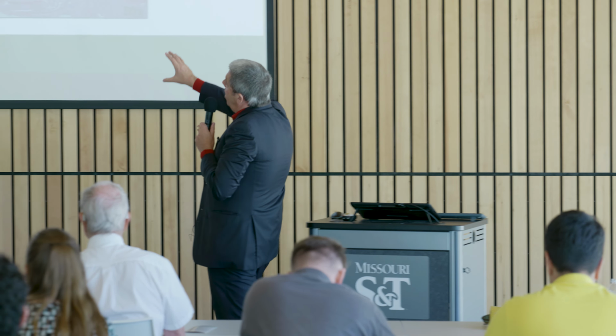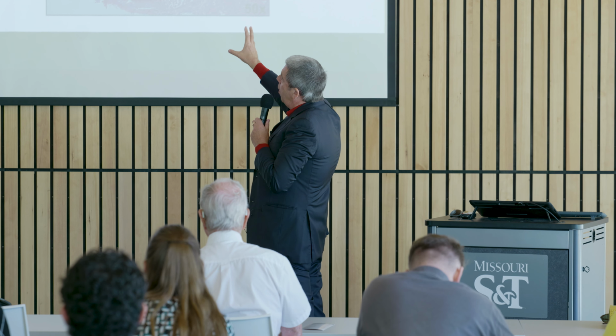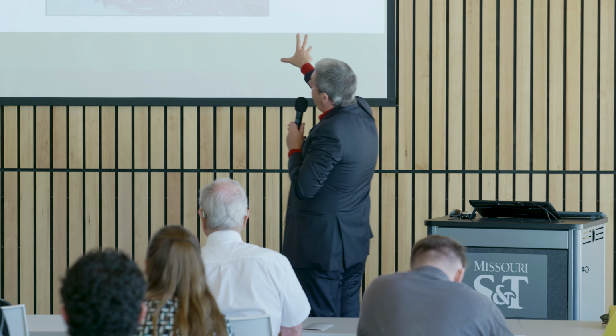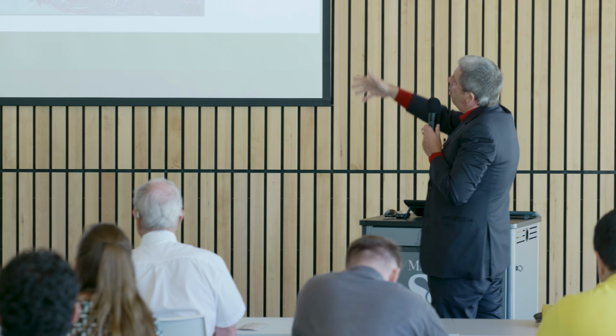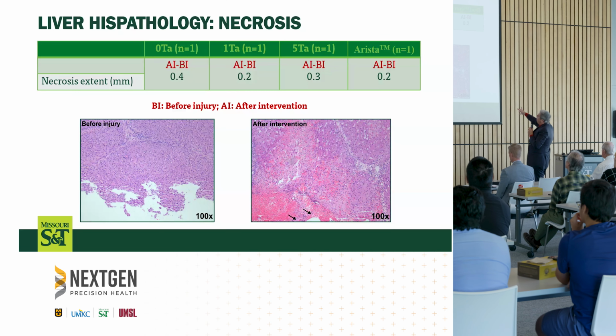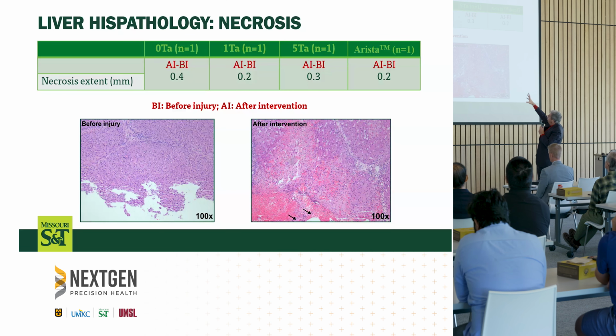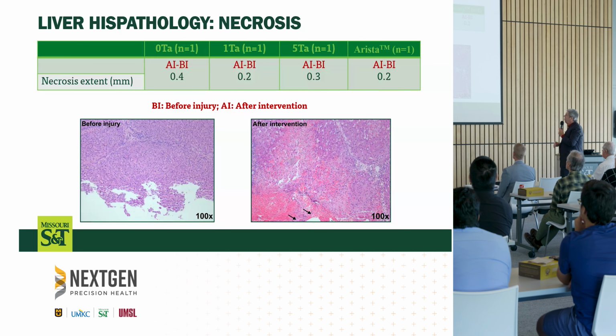What we can see is a little bit of liver histopathology, where we took samples of the liver from the Arista-treated pig and from our material, and we found that the amount of hemorrhage, amount of bleeding, was about the same for our material as for Arista. Slightly higher, but nothing to be concerned about. We also saw the tissue necrosis, the death of the tissue, was roughly the same regardless of the intervention, Arista or our MBG.